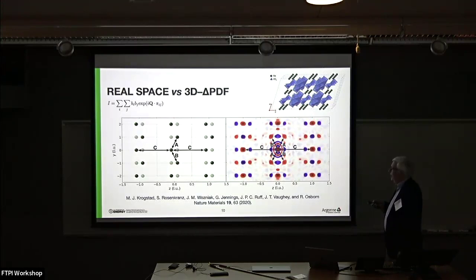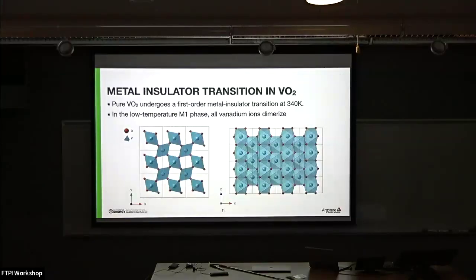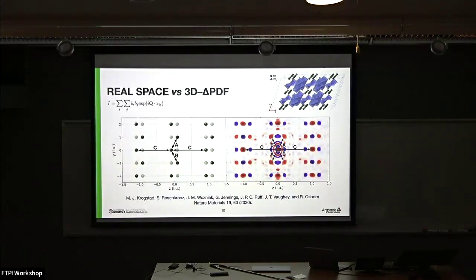And if you look at the probabilities, you see blue peaks. That means all crystallographers can tell us is that there are these two-leg ladders, and that the sodium sites are occupied with 50% probability. That's what you can determine from a crystallographic analysis. You can't tell what the local correlations are, but with a 3D-ΔPDF you can.